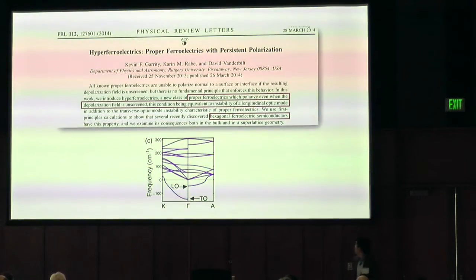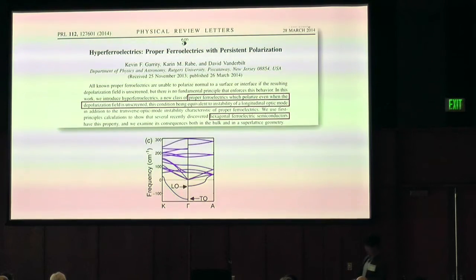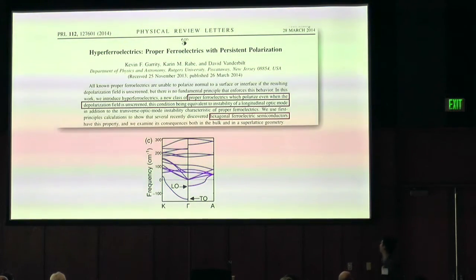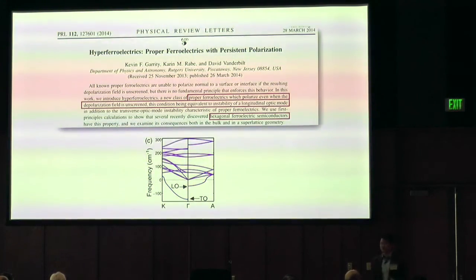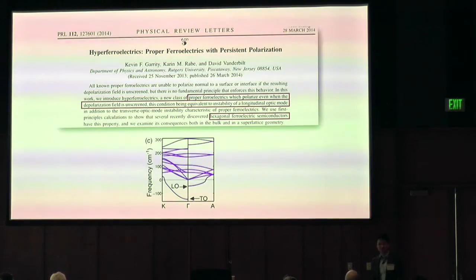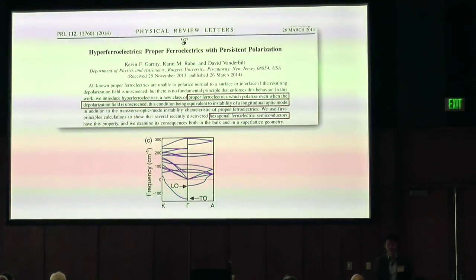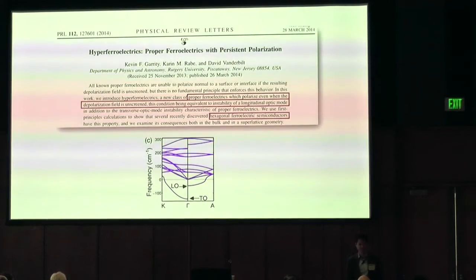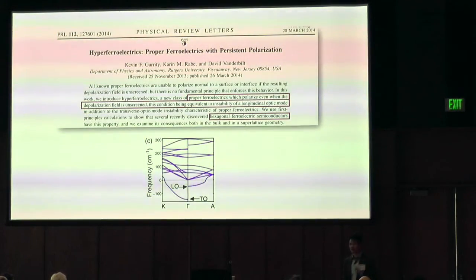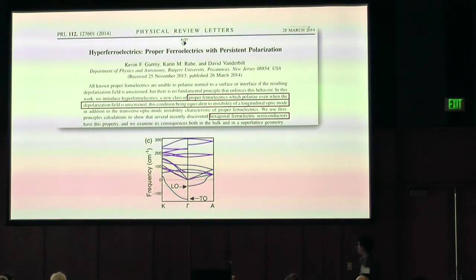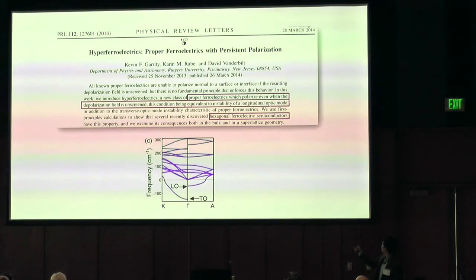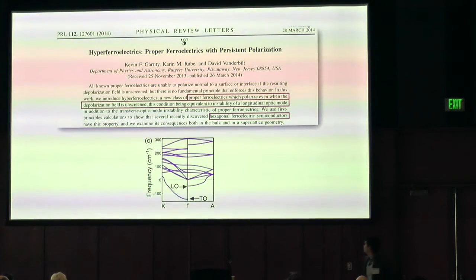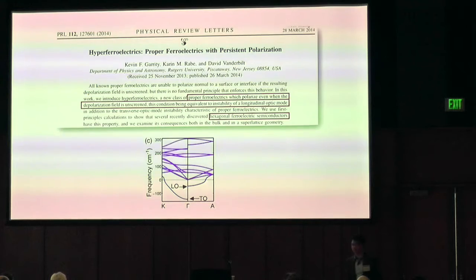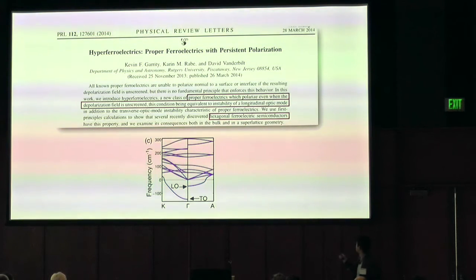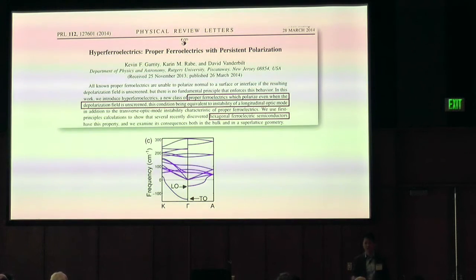And the idea was that they predicted this new class of materials called hyperferroelectrics. So these would be proper ferroelectrics that would be stable against the depolarization field. You could make them much thinner. And the key thing to look for would be this sort of unstable LO phonon. And this first paper was predicted in this specific class of materials that are these hexagonal ABC ferroelectric semiconductors.